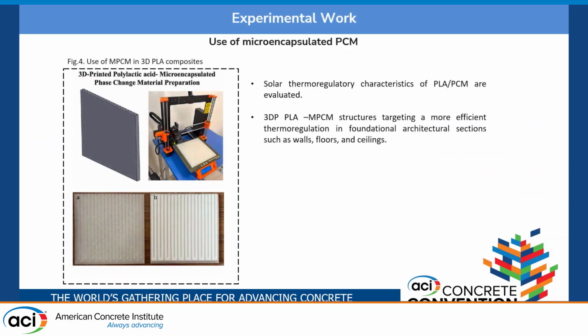Unfortunately, regardless of the incorporation method, phase change materials affect the mechanical performance of the concrete. So that's why we thought maybe we can incorporate these materials into some other polymer structures that we can use as an architectural element, such as in between the wall members, or ceilings, or floors, or roofs. So we have 3D printed polylactic acid composites, with some tubes and holes, and we have incorporated our microencapsulated phase change materials in this. As we are using a lot of PCM in these composites, definitely we're expecting more thermoregulatory performance here.